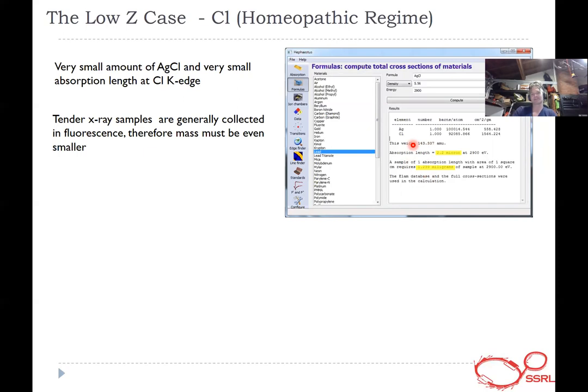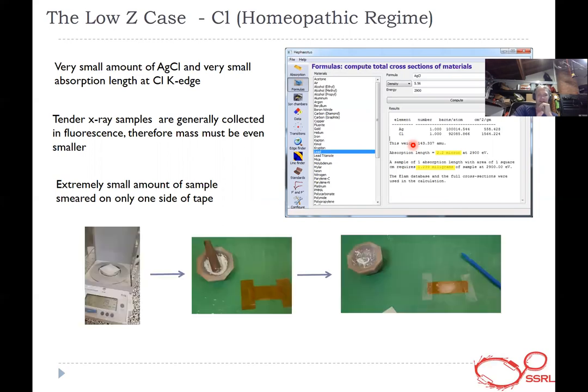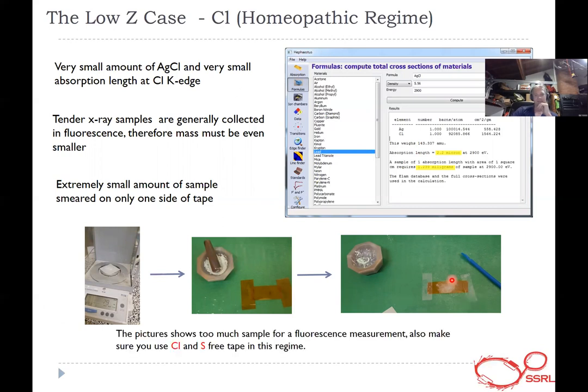So for these types of experiments, they are always collected in a fluorescence regime. And therefore, the mass must be even smaller, and that's where I get at the homeopathic. You just want a dusting, if it's a high concentration sample, of the sample on the tape on one side, because X-rays are actually absorbed significantly by Kapton and polypropylene tape, a fair amount at this energy. So here again, weigh it out, grind it up, and then smear it here. Even this is probably too much sample in some cases for silver chloride. So definitely talk to your beamline scientist about your sample preparation before you get here.